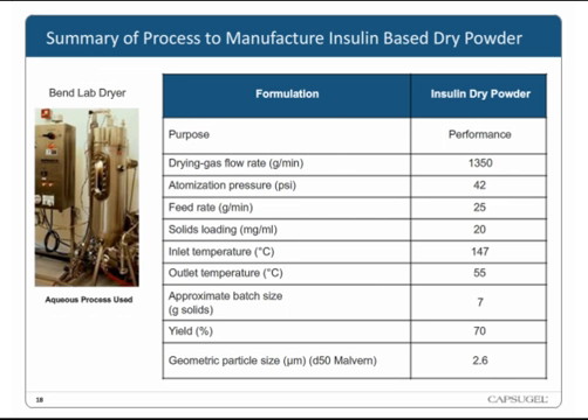And then in this case, we were looking at an approximate batch size of about 7 grams, and at this small scale getting a yield of 70%, which typically, as we scale these formulations up, we start to get higher into the 80 and even 90% yield. And we did perform, using a Malvern dry powder method, a geometric particle size measurement and showed that we were getting about 2.6 micron particle size.